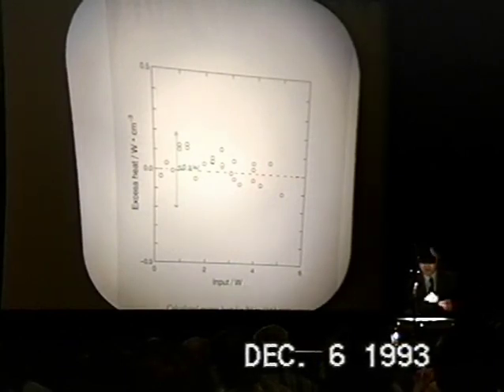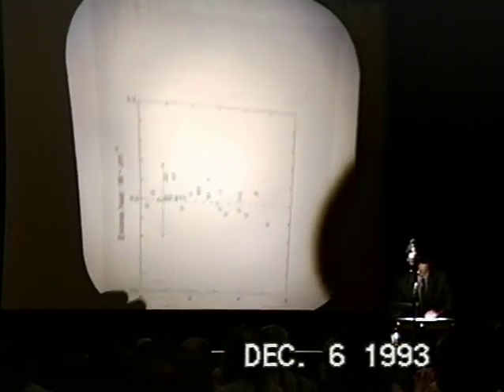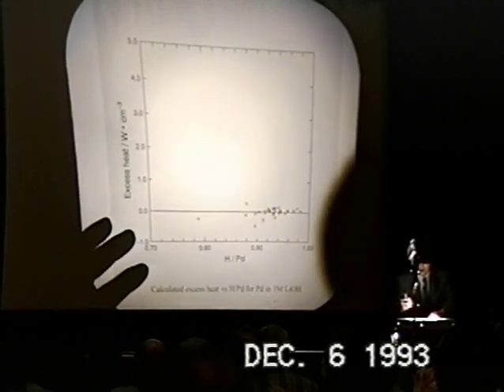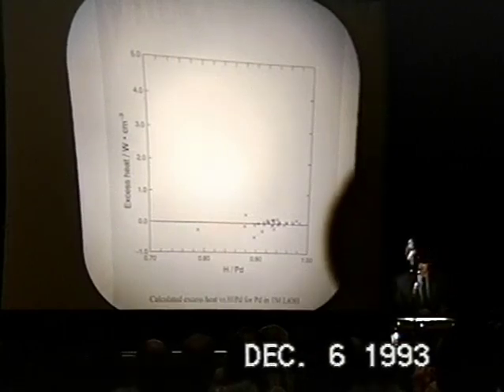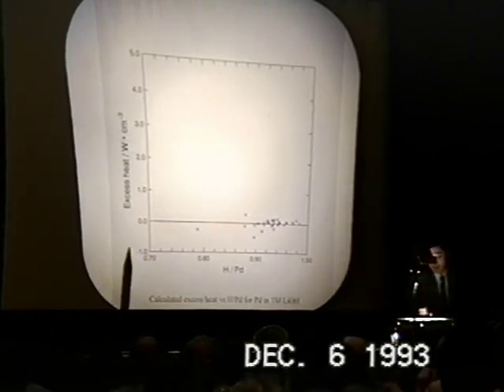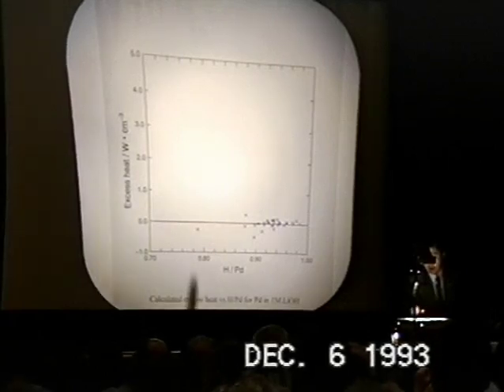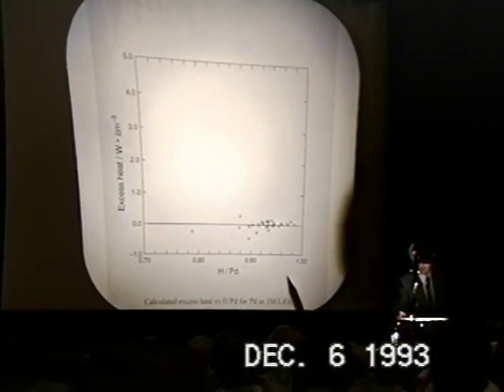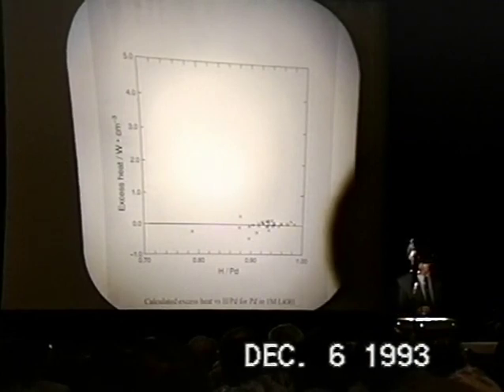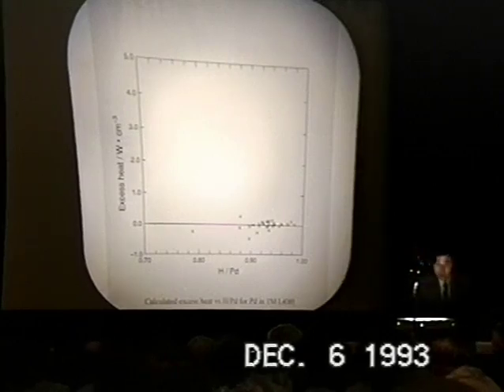And again, this tells us not only the accuracy, but also the absence of excess heat in the light water system. If we compare the data on palladium and data at the nickel cathode, this is excess heat expressed in terms of watt per cc as a function of H over Pd. So for hydrogen system, we can go to very high loading ratio, very close to 1, but up to 0.99, we see very, very little deviation from the zero line to show actually no excess heat for this system.